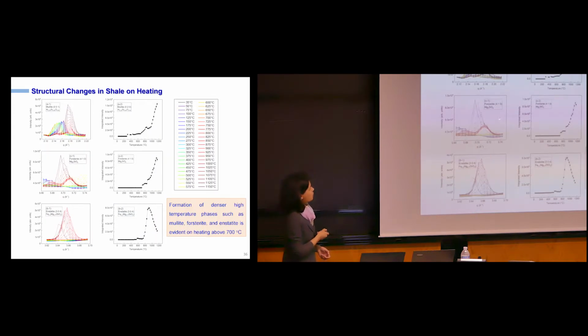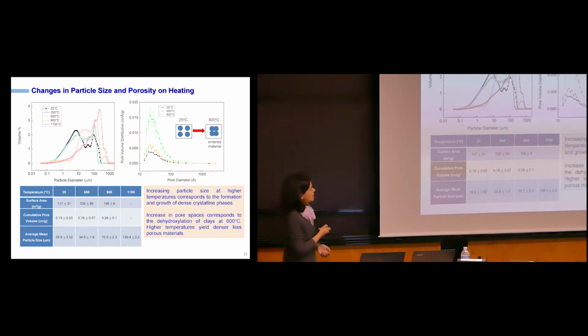And we end up forming these very, very dense silicate structures instead. These silicate structures tend to fuse, and you get much larger particles, and you also squeeze out the little porosity that's present, right?